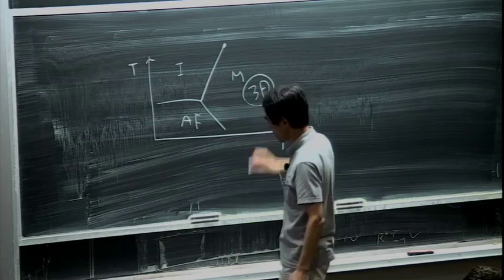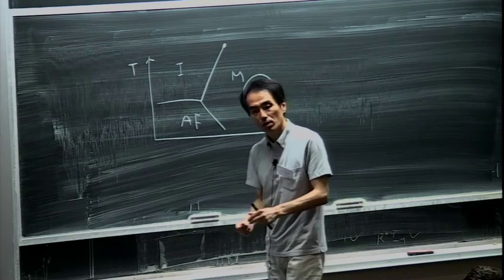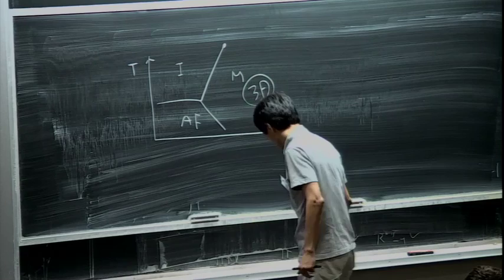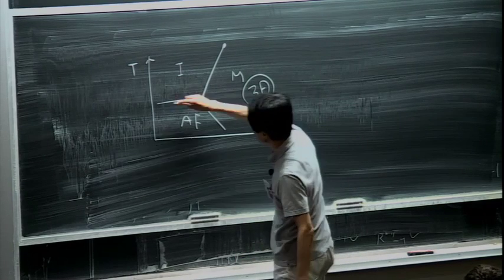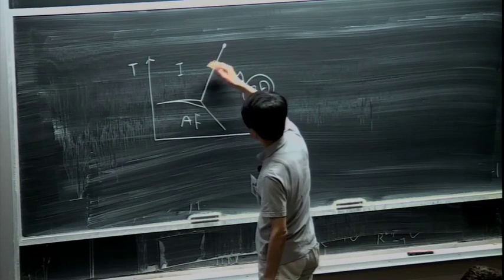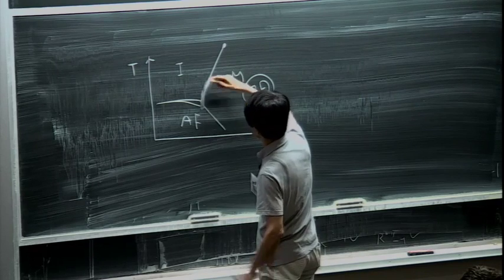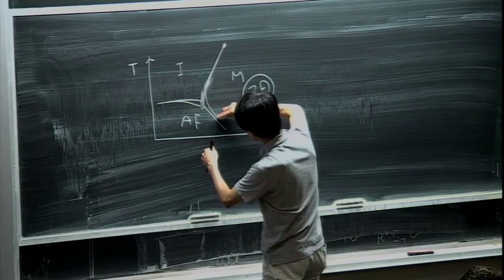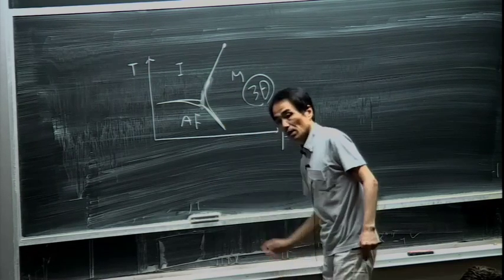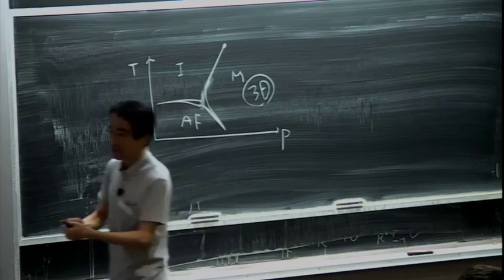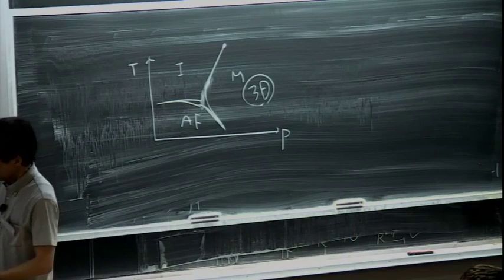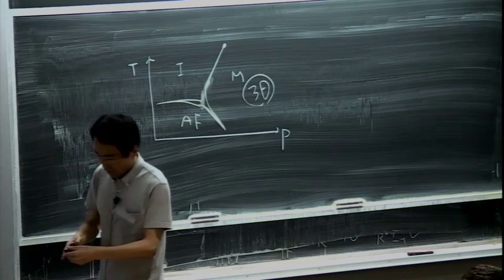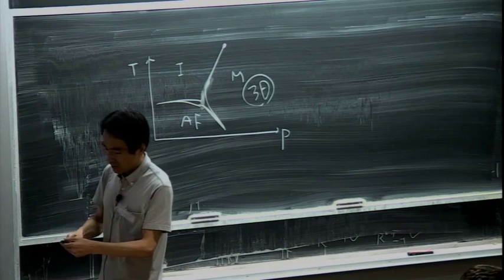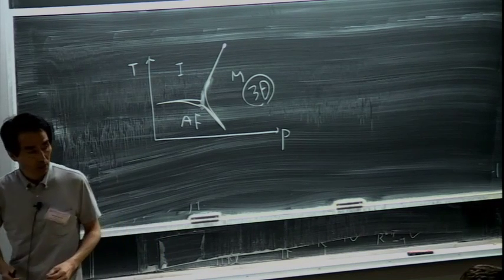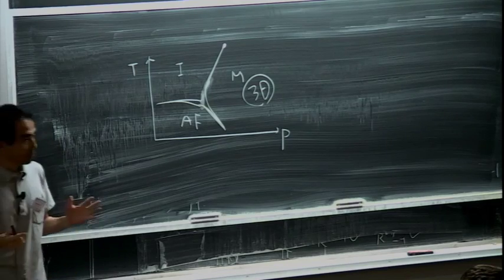But in a very strongly two-dimensional case, at high temperatures, magnetic order like this, but still at high temperatures, it's short-range order, like this. This is the explanation of this phase diagram. Okay, and from the phase diagram, we can guess how the entropy dies out at low temperatures.